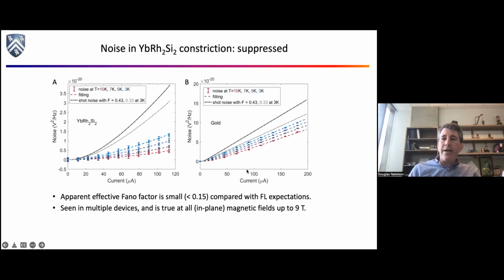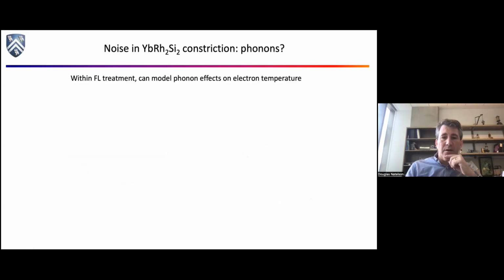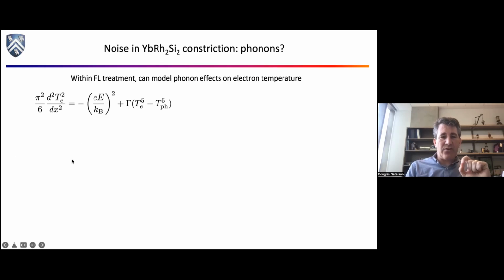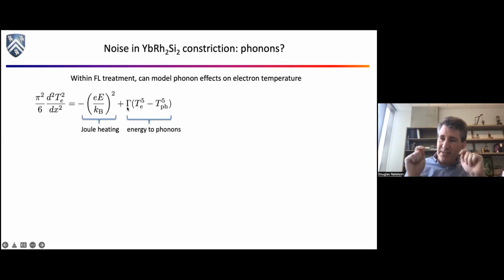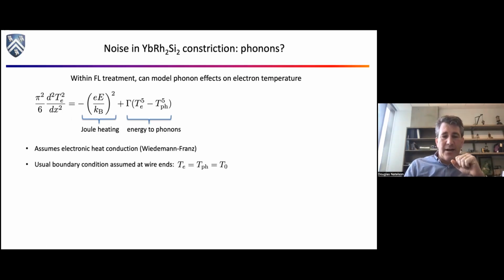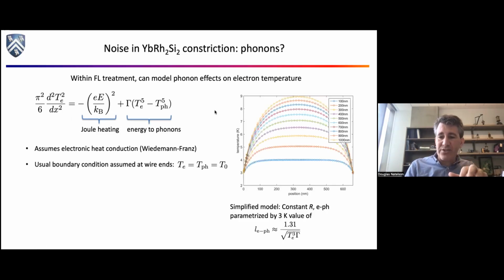Now, you might wonder, maybe my phonon story from the gold is being reproduced here in the ytterbium rhodium 2 silicon 2. Maybe it's phonons. Maybe it's the lattice that's squishing everything. We don't think so. You can model this. There's ways to actually do a real calculation. I can go over the details if people want. But what really matters is this gamma. This is basically the rate at which energy gets lost to the lattice. And you can do all these calculations and play games with what you think that coupling constant is.